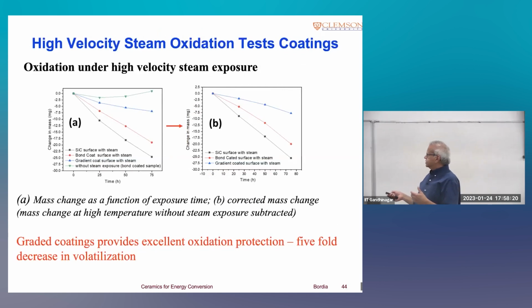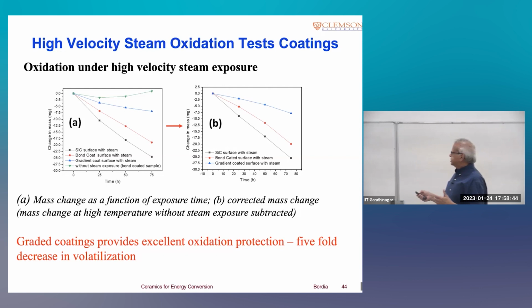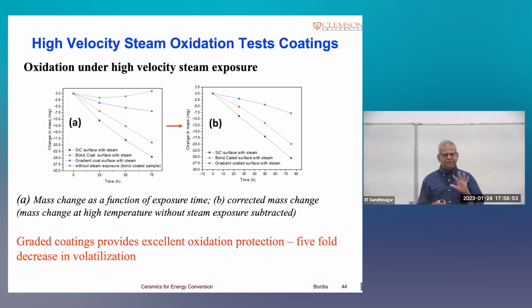But the more important result is here, which shows that when we did not have any coating, because of the high velocity steam, you got significant mass loss. So these are only hours. And in these hours also, we got about a few % mass loss from the silicon carbide. By putting the coatings, we were able to reduce, so this is actually the corrected data. So this is without coatings, this is with coating, and the reduction in the recession rate was about a factor of 5. So it's sort of early on in this project, but already we are showing that you can dramatically improve the oxidation resistance of silicon carbide by putting these kind of coatings.